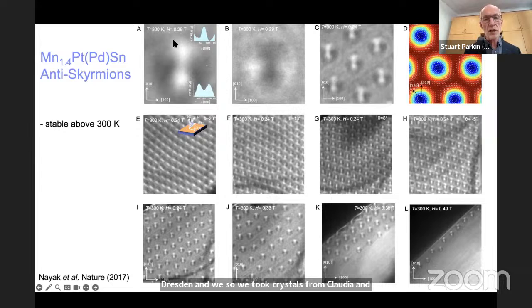And we could see for the first time an antiskyrmion. And you can see it clearly looks like this predicted clover leaf-like structure. And as in the microscope, we can vary the temperature and the magnetic field. These are actually at room temperature. And you can see that the antiskyrmions typically form hexagonal arrays of these objects, as shown on the top.